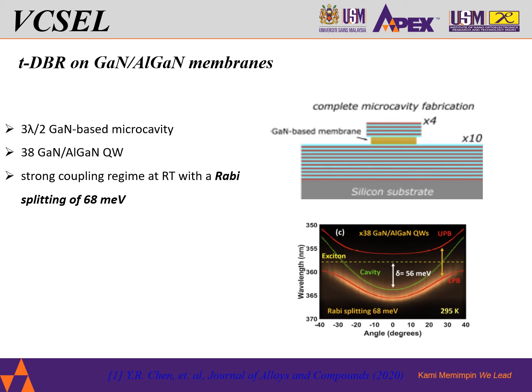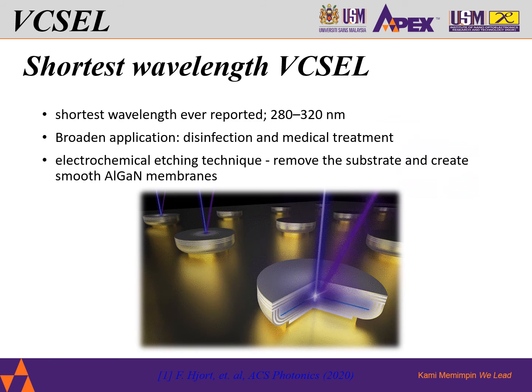Those fabricated 4 pairs of TDBR are then transferred on top of this GaN-based membrane containing 38 GaN/AlGaN quantum wells on top of 10 pairs of the same DBR on a silicon substrate. This results in a strong coupling region with a Rabi splitting of 68 meV at room temperature. The shortest wavelength VCSEL ever reported as of 2020 is in the range of 280 nanometers to 320 nanometers. This can broaden the application towards disinfection and medical treatment.